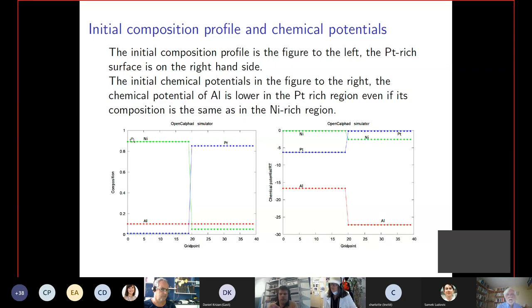So I set up a composition profile where you have mainly nickel and aluminium in the center of the turbine blade, and you have mainly platinum in the surface. I took the same aluminium content in the surface also, and the nickel disappears in the surface. And this is the composition. You have 90% nickel here, 10% aluminium. You have 85% platinum and little nickel.